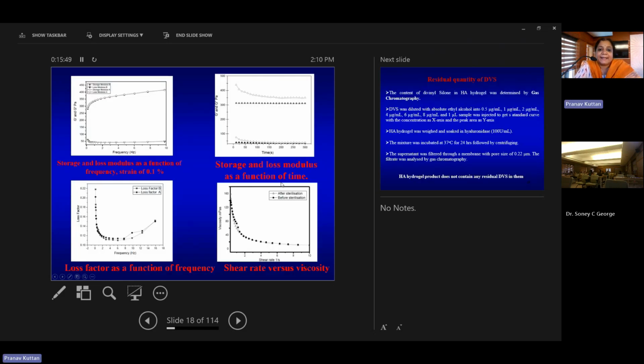And this is actually the detailed rheological analysis. First one is the storage and loss modulus. Like you will be knowing that hydrogel, when you study the rheology, you will be evaluating the viscoelastic properties mainly. That is the storage modulus, which gives an idea about how strong this gel is, and the loss modulus, which gives an idea about the liquid-like parameter of the hydrogel. So we can see that it has a very strong storage modulus, indicating that it is very strong, like stabilized hydrogel.